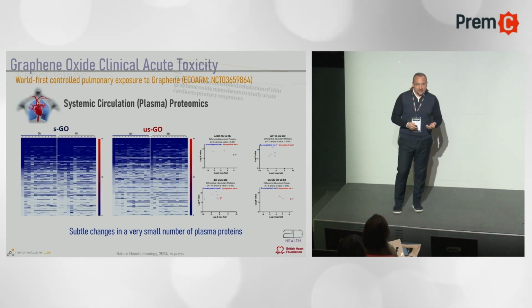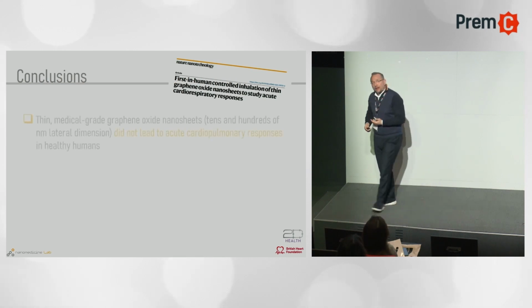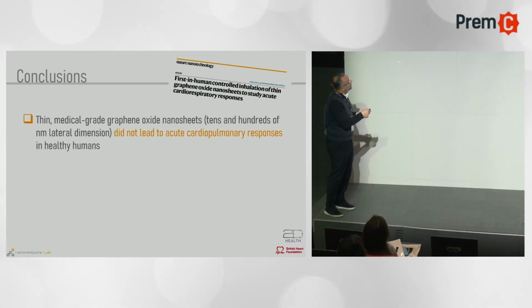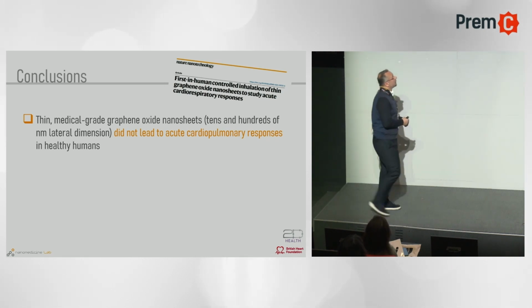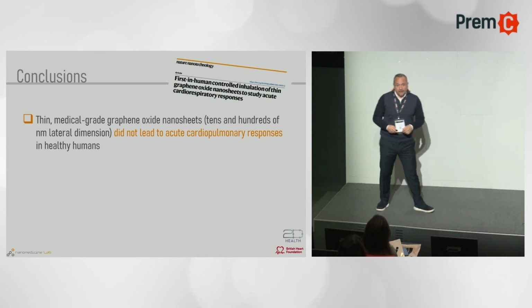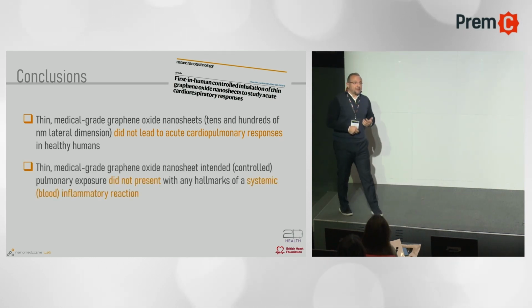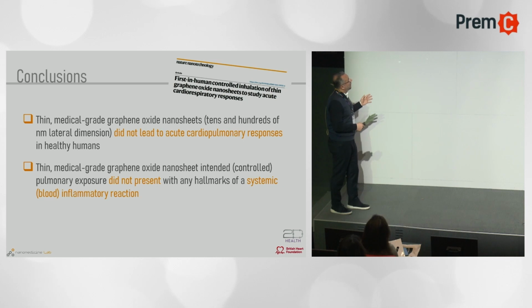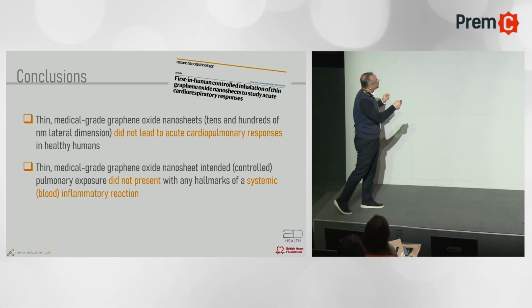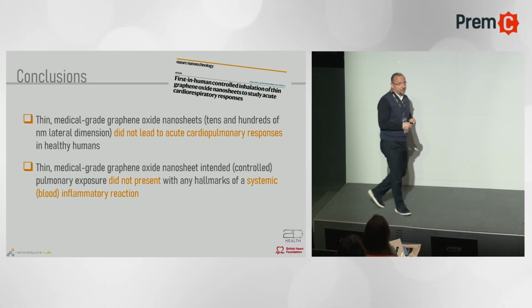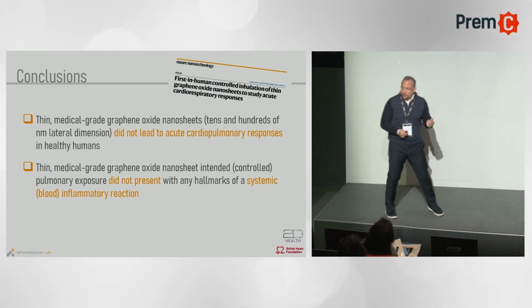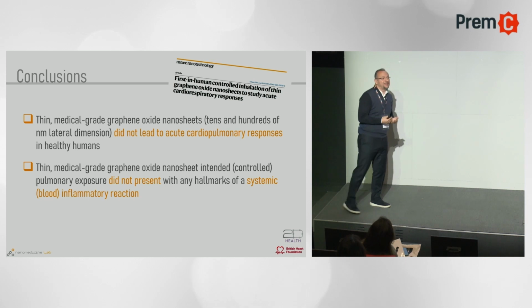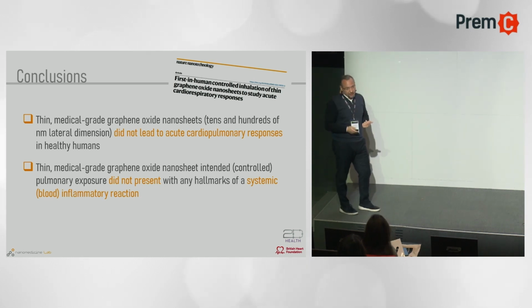All of this suggested that, first, our thin medical-grade graphene oxide nanosheets that are in the tens and hundreds of nanometers in lateral dimension did not lead to an acute cardiopulmonary response in healthy volunteers. The second, that the same material that was intended for pulmonary exposure did not present with any hallmarks of systemic inflammation, which was also very important to see if we trigger any systemic inflammation from acute exposure.